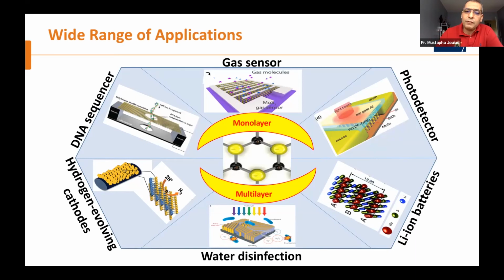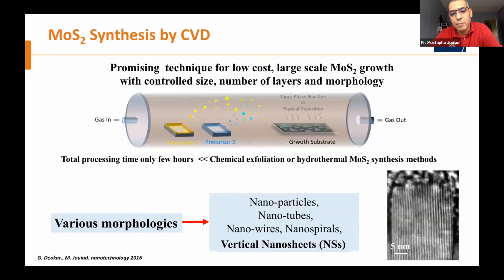For our case, we developed a new technique to make this MoS2 straightforwardly and easily, just by using CVD with sulfurization. You can see here in this tube furnace, I just put a schematic of what's going on. We put sulfur as the first precursor and molybdenum oxide as the second one. Then we can choose any kind of substrate, and we are able to produce our MoS2 materials. Basically, we obtain different morphologies, and they are all documented. Today I will talk only about the needle-like shape, the MoS2 that is aligned vertically to the substrate.